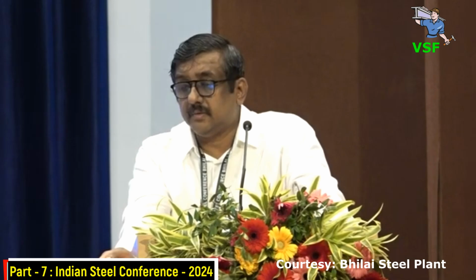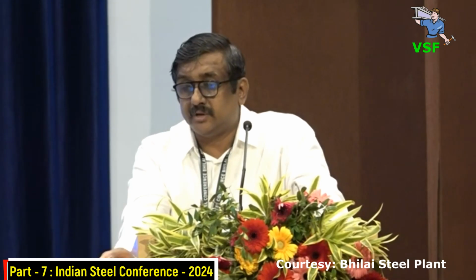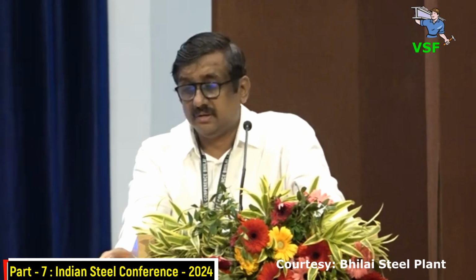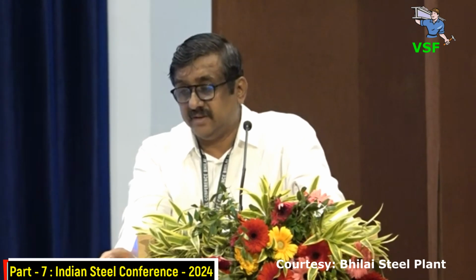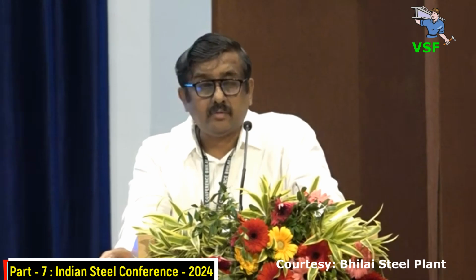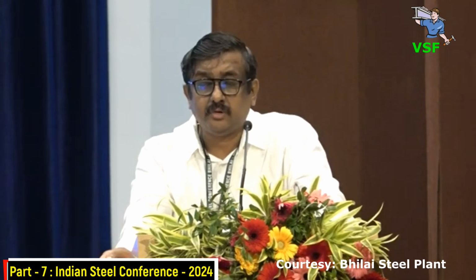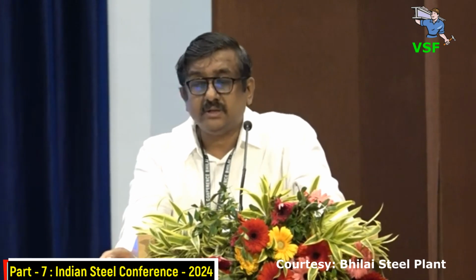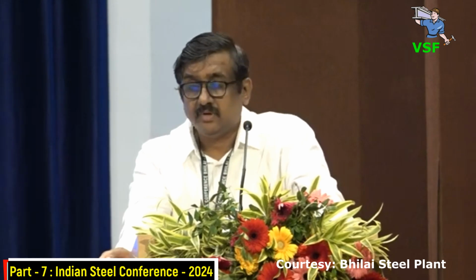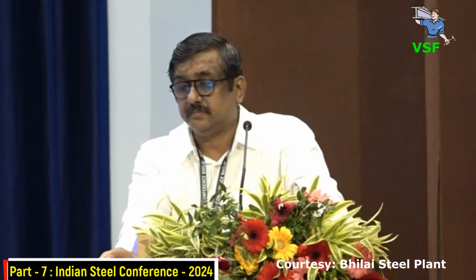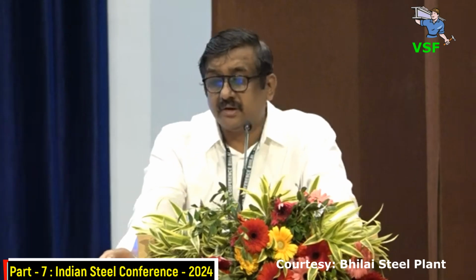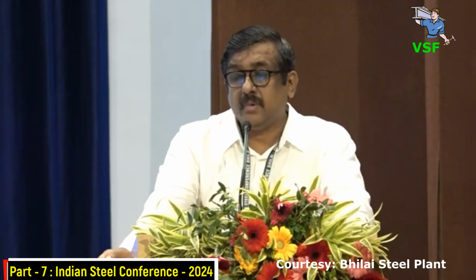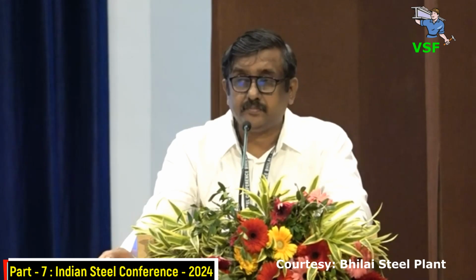The SP3 team, which I have already said is doing an excellent job, has already fixed the columns and the base. In the next shutdown of around 16 to 20 hours, we will be installing the hood, which is being shown here. It will result in a reduction in coke breeze consumption by 2 kg per ton of sinter.